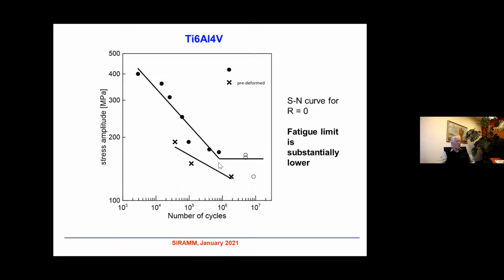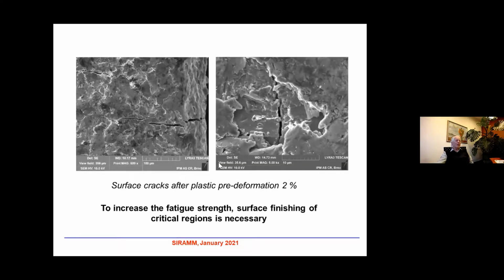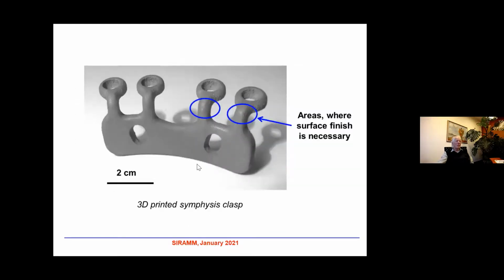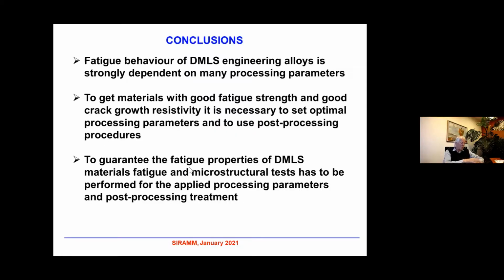So it is a very important result, and it means that during this small plastic deformation, since the beginning, in the surface layer, cracks appear, and these cracks can then propagate very easily and result in a very low fatigue limit. So to increase the fatigue strength, surface finishing of critical regions of components is necessary. In our case, it means that these areas which are bent by the application of this implant should be polished in a sufficient way. So, ladies and gentlemen, I was perhaps a little bit longer. I apologize, and let me conclude my talk.